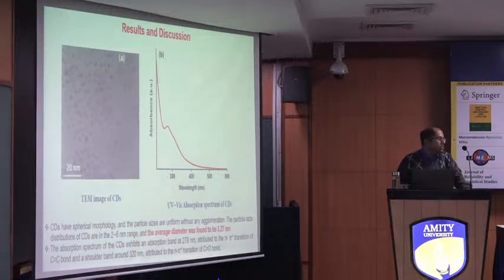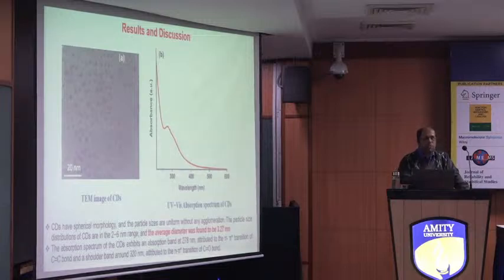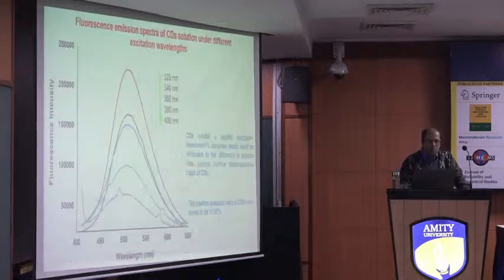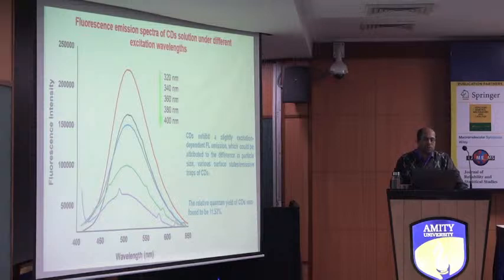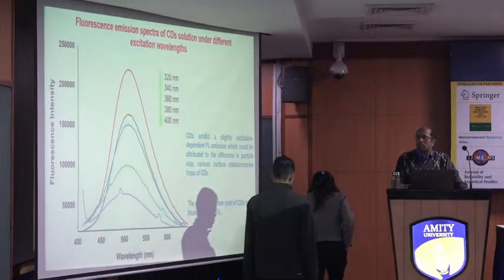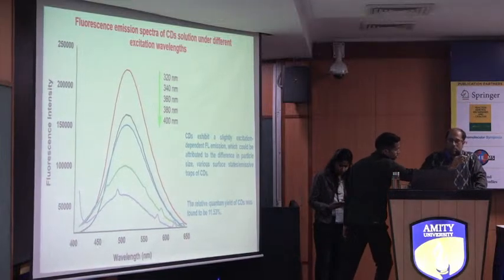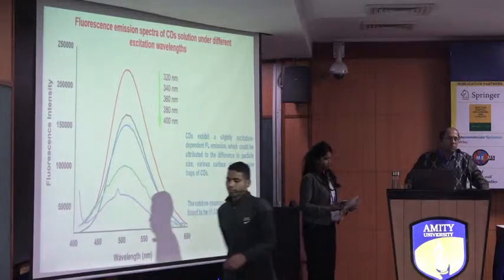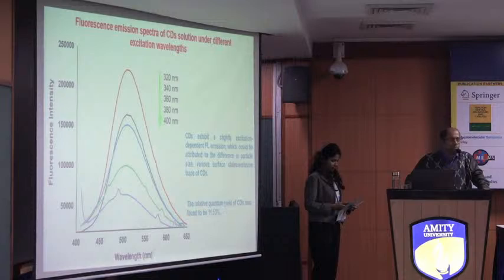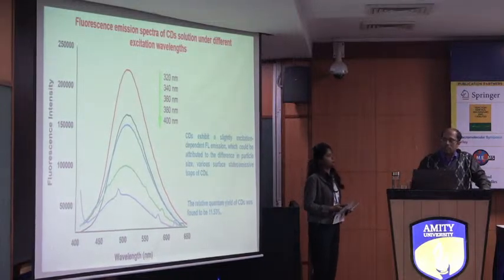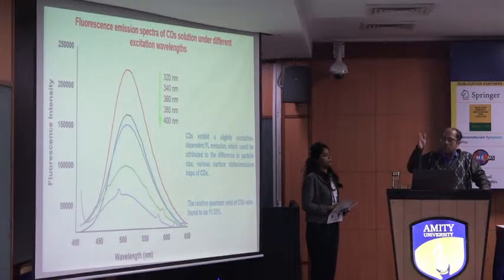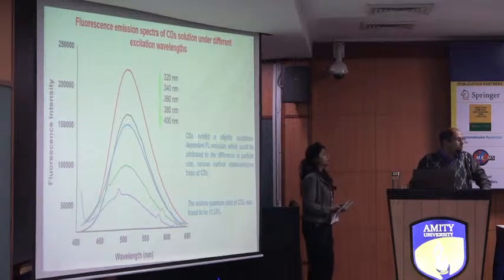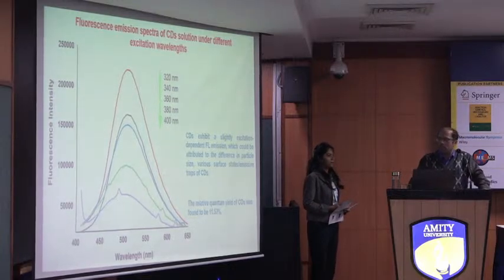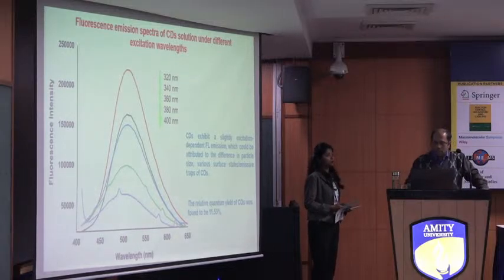To study the optical properties, we performed the UV absorption spectrum, which showed an absorption band at 278 nanometers along with a shoulder band around 320 nanometers. Further, to study the photoluminescent properties, these carbon nanodots were excited from excitation wavelengths ranging from 320 to 400 nanometers. As you can see, there is a slight shift in the emission peak as we excite from 320 to 400 nanometers. This is mainly attributed to the difference in the particle size present in the quantum dots, and sometimes it is due to the different surface states or emissive trap states present in the carbon nanodots.